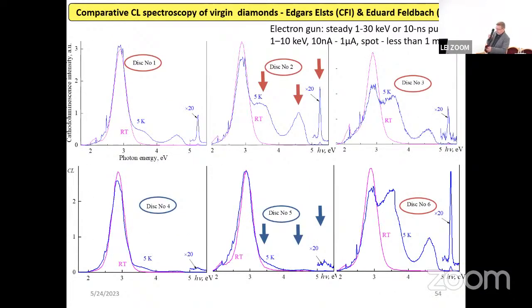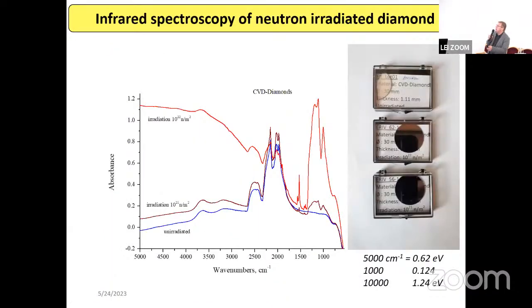You can see that all disks are different, but after this data we sent some recommendations to the company on which disks are good and which are not yet, just to find the best technology to produce larger such disks. And this is just an example. This is non-irradiated. Unfortunately, this disk was broken. But you can see that it is transparent, because it was irradiated by neutrons, and we have two disks irradiated with neutrons. This is just the result of the infrared measurements. Interpretation of all these peaks was done.